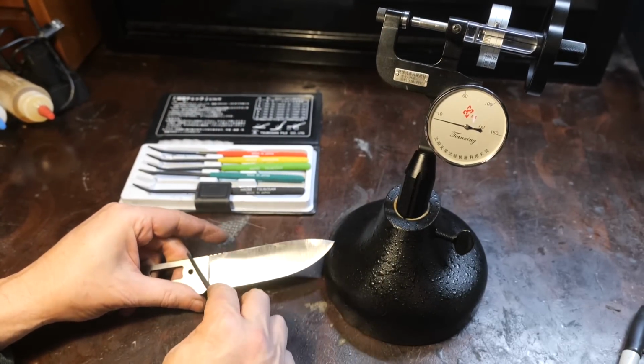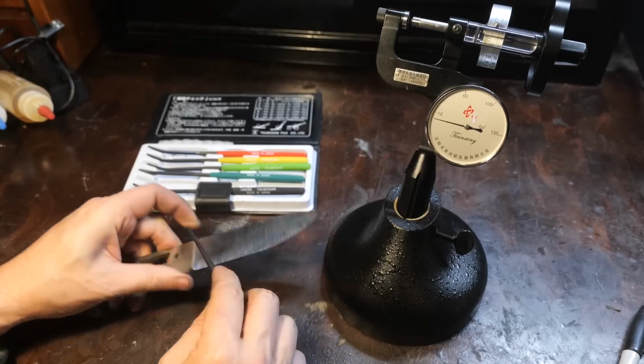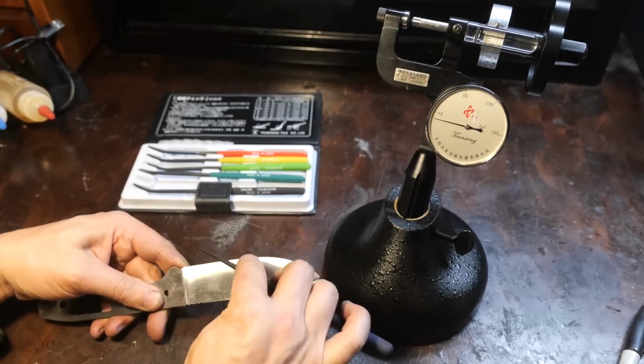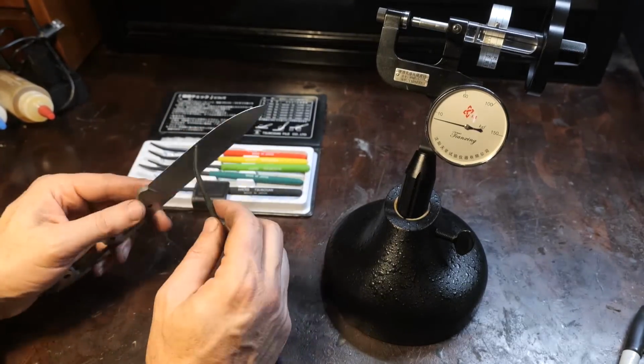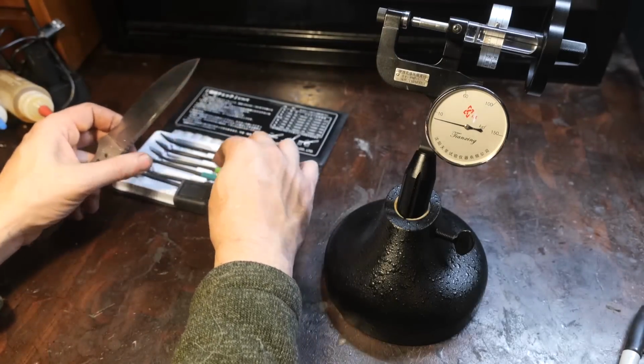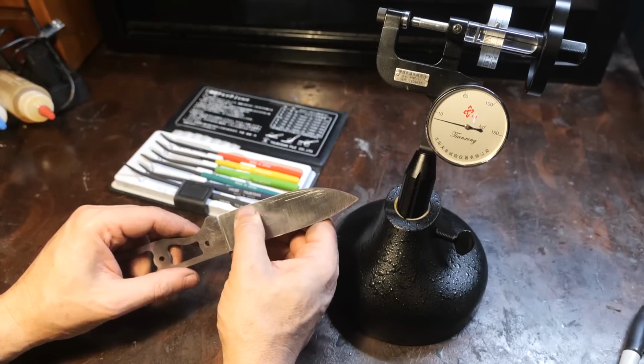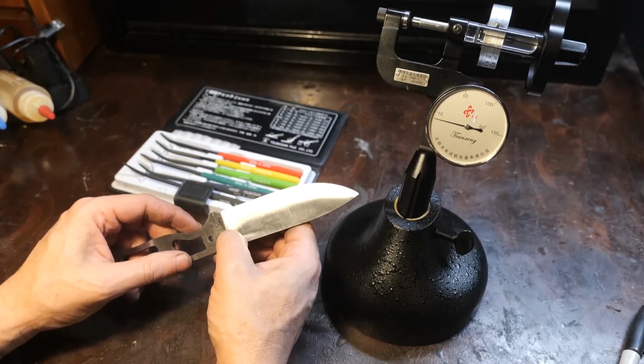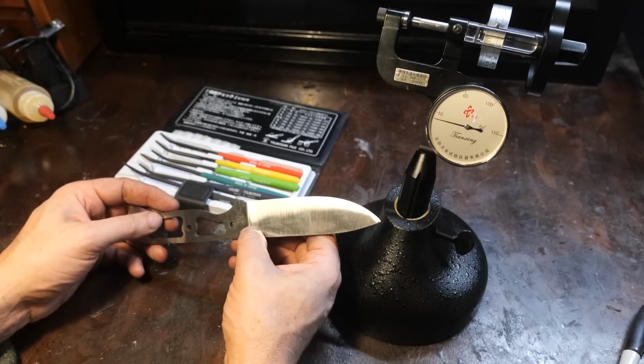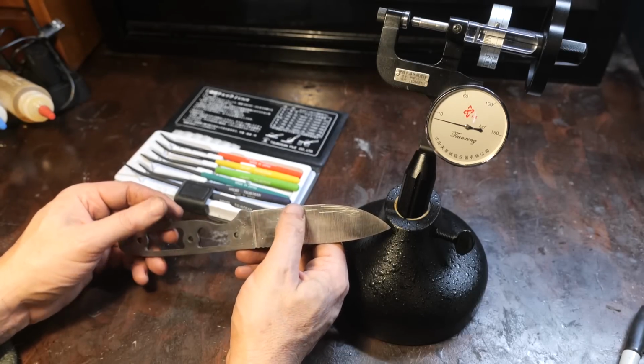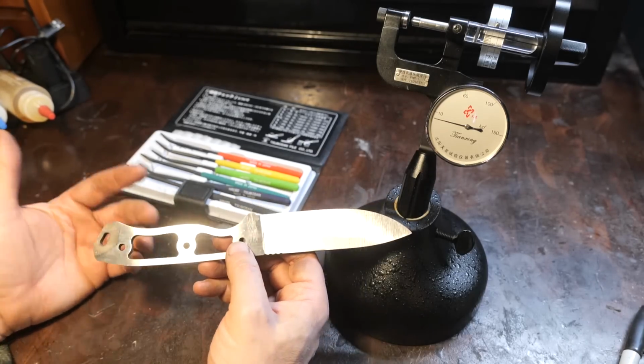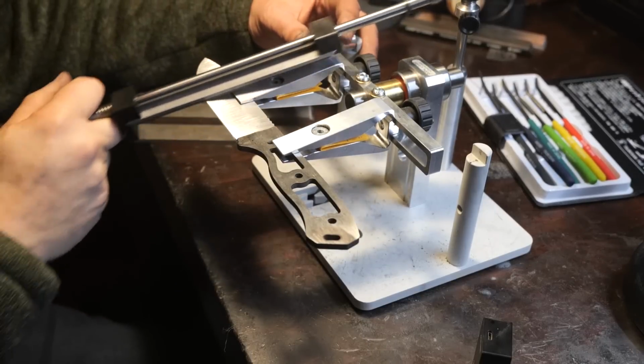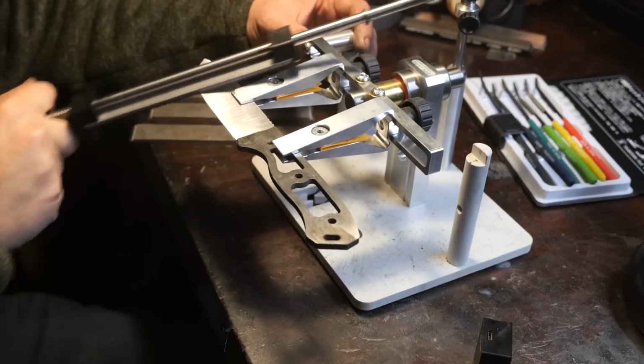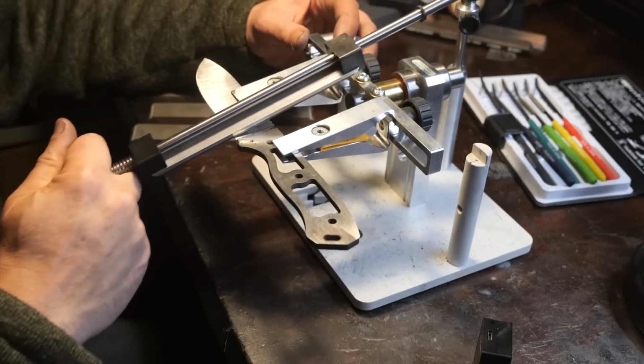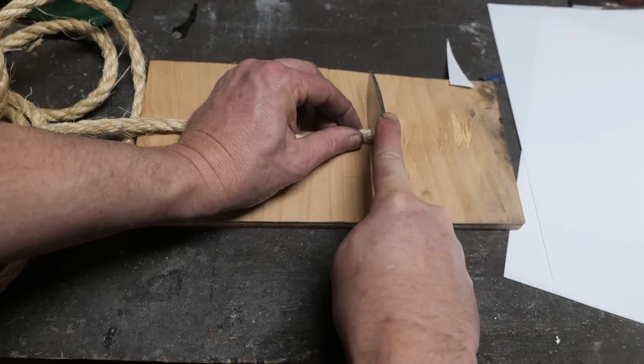Some areas it digs in, others... I'm having to check this several times because the results are in a wide range, anywhere from 58 to 61.5 with the portable tester. Now maybe there are soft spots from not getting rid of all the decarburized steel. I'm not really sure, but ultimately I think this comes out right around 60. This time I'm going to sharpen the knife to 17 degrees per side. Let's see how that does. I think that'll do a lot better than the 19 and 21 degrees it came at.